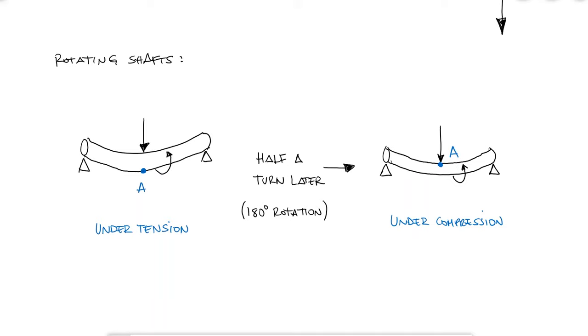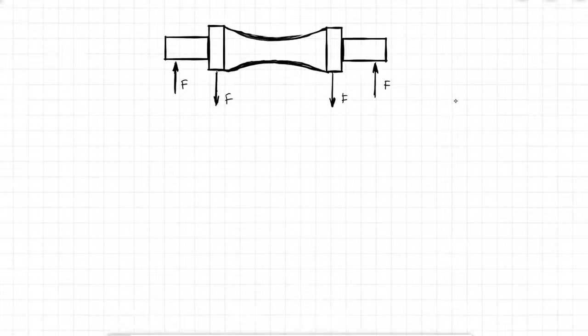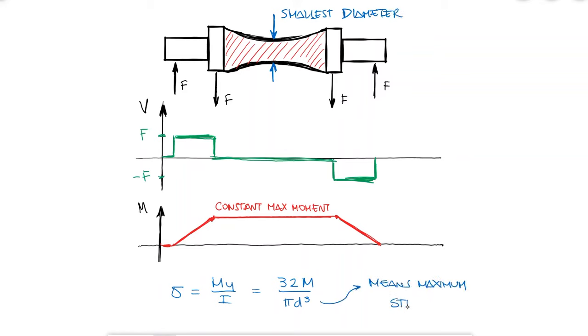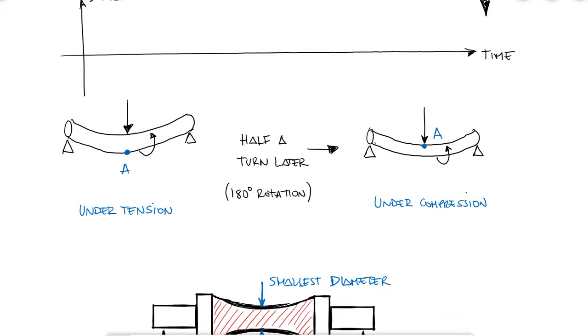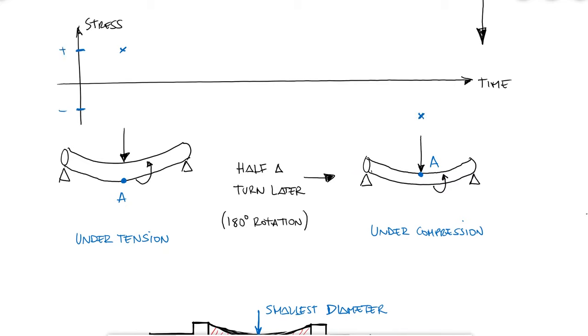This notion is exactly what we use to experimentally measure this fatigue strength property that I mentioned before. A bending machine is used on a specimen to cause a known bending stress that is highest at the center. If we look at a quick transverse shear and bending moment diagram, we see that the moment is constant throughout the middle section. And because the cross section area is smallest at the center, the maximum bending stress will occur exactly there. Since the specimen is constantly rotating, a specific point on the surface of the rod will go from a positive normal stress, tension, to a negative normal stress, compression, of the same stress value, and of course, everything in between.